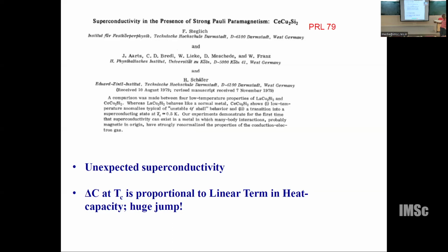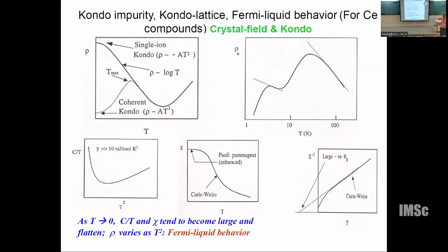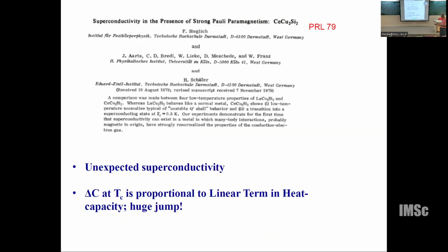So delta C, I'm talking about students, delta C should be proportional to the electronic term, right? In these materials, the electronic term is huge. They find delta C is also enhanced by three orders of magnitude, like the effective mass. Therefore, this is called a heavy fermion superconductor. This was discovered for the first time. This thing is called a superconductor, and it is supposed to be an unconventional superconductor.